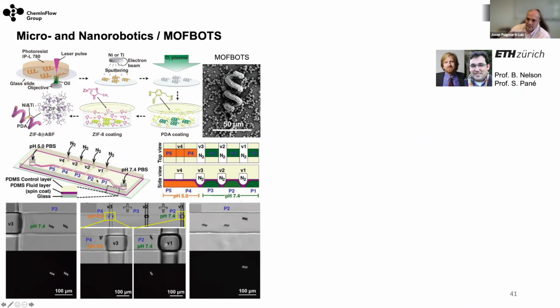So what you can see is that we added these micro robots at pH 7, and then we injected 4 of them. 2 of them stayed at pH 7, but 2 of them we moved to pH 5. What you see is that now these 2 that were fluorescent lose the fluorescence, whereas the ones that stayed at pH 7 still keep it. So here is what happens when we brought back the 2 micro robots that were at pH 5. You see we have the 4 of them. These are entangled now, so they are still fluorescent, but these 2 lost the cargo. They lost the rhodamine that they were carrying in the porous structure. So this is just to give an example.